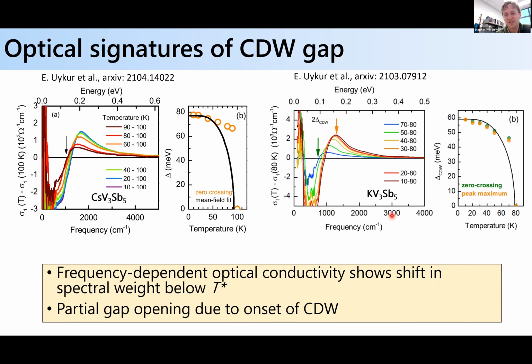They can do the same exercise with the potassium system, and again they see these spectral signatures of an optical gap opening below this transition temperature. And it's consistent, again, there's still spectral weight below the gap, right? So it's consistent with a partial gap opening due to the onset of this charge density wave state.